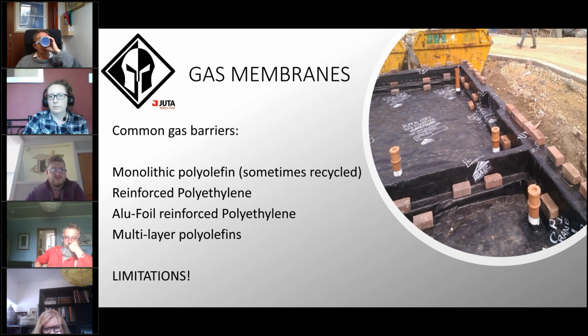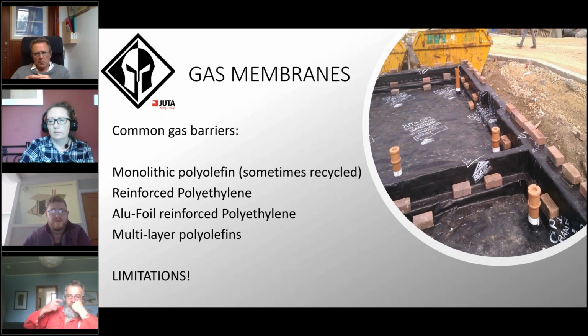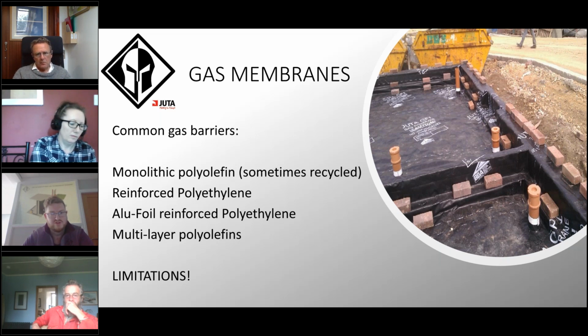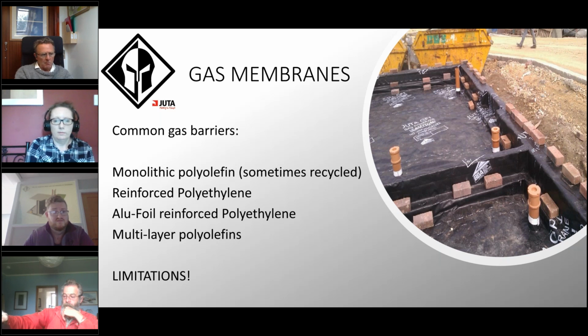And then we have this new breed of materials, which are the multi-layer polyolefins. So these are 5 or 7 layer products, usually with an EVOH barrier in the middle and then protected by various layers of polyolefin on the outside with no aluminium in them. But all of these materials have various limitations, and what we don't do as suppliers or manufacturers is shout and scream about the limitations. I mean, why would you? JUTA is the biggest supplier of aluminium foil gas membranes into the UK, and 50% of the jobs we're supplied onto, we probably shouldn't be using it there because of the limitations, but we're not the regulator. So if the clients, end users, engineers, architects don't want to listen to us, then that's on them.